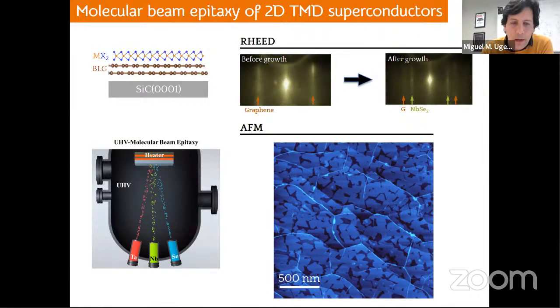And in this case, we use pure niobium and pure selenium. All we do is keep our substrate heated. We apply some heat to keep it at high temperatures while we perform the growth. We can track the evolution of the growth using RHEED in situ. Here I show you the diffraction patterns coming from graphene before the growth, and the emergence of some additional lines, some additional diffraction pattern that comes from our TMD.